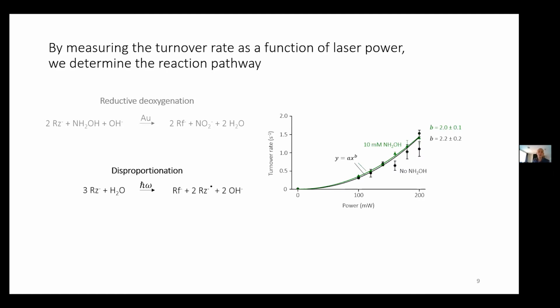And of course, this is quite an interesting observation because if the reaction is photo-driven, then that would suggest that the plasmonic near fields are the driving force behind this chemical reaction. So that then also suggests that there should exist some sort of spatial correlation between the positions where you have high electric field and the positions where you observe high catalytic activity. So what we are going to do is simulate the electric field around the nanorods and see if the positions where we observe hotspots are also the positions where we observe high catalytic activity.